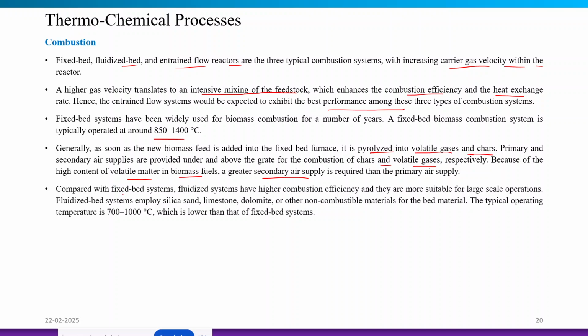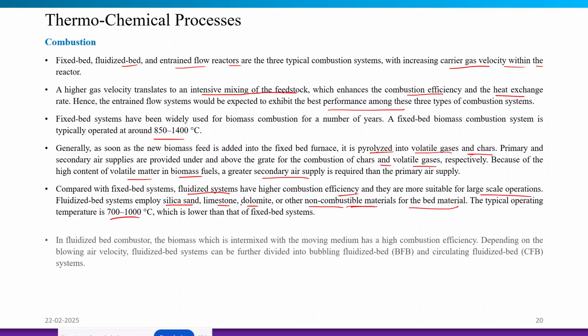Now, compared to the fixed bed system, the fluidized bed system has higher combustion efficiency, and is reported to be more suitable for large scale operation. Fluidized bed systems employ silica sand, limestone, dolomite, and other non-combustible material as the bed material. The typical operating temperature is 700 to 1000 degrees for the fluidized bed, which is comparatively lower than the fixed bed system.